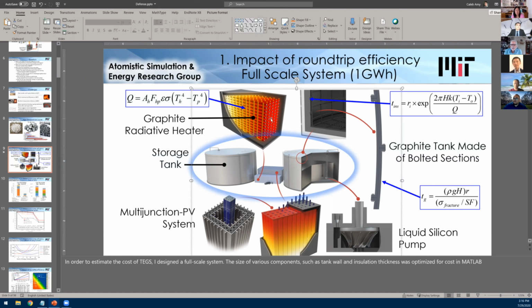That's a similar thickness to what you use for the TPV system also, right? Yeah, yep. Anywhere where there's heat transfer through the pipe, the wall thickness that we use is about 5 millimeters. What's the thermal conductivity you assume at that temperature range? It's about 30 watts per meter Kelvin. Graphite's much more conductive at low temperatures, but at this temperature, it drops to around 30, maybe 35 watts per meter Kelvin.